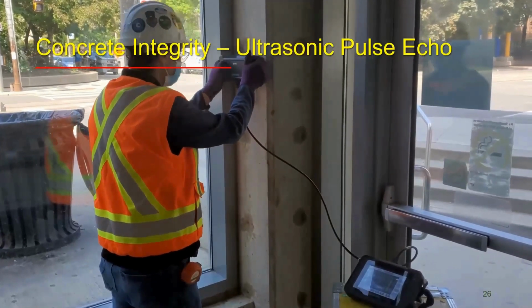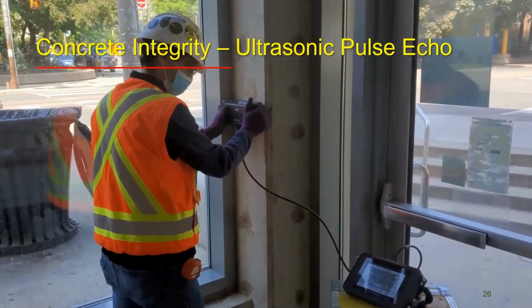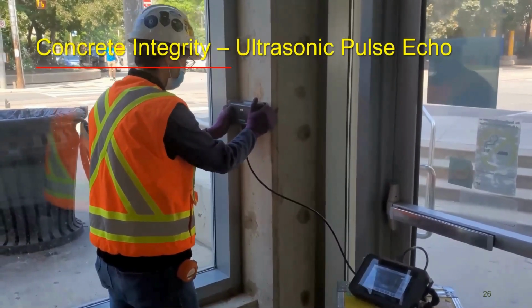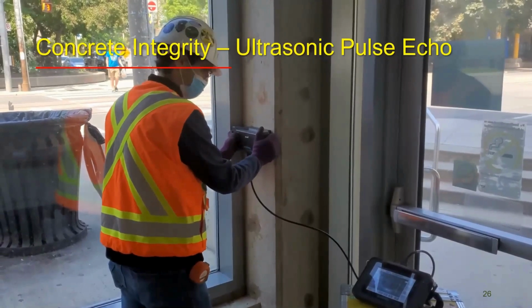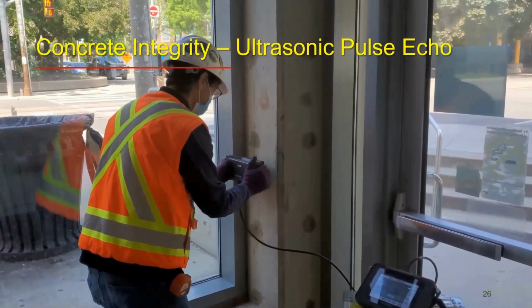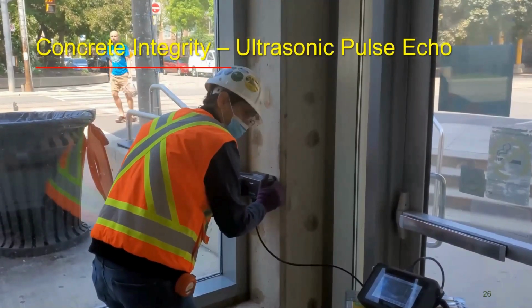And the practice is quite simple. If you have the right tool, you will be able to evaluate the quality and the integrity of the layers. You will see if there is any major delamination or discontinuity in the concrete element. At its most basic use, you can use UPE to verify the thickness of an element. Let's say you have a bridge abutment 40-50 centimeters thick, and you want to see if the element meets the design requirement. In more advanced applications, you want to see if there is any void or any significant anomalies within the concrete in depth, and the test provides very useful information.